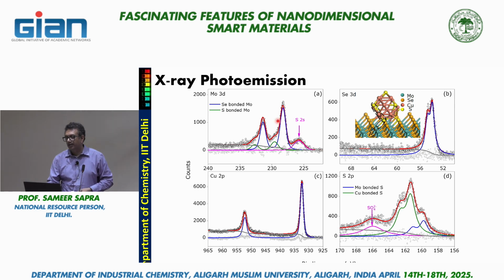and molybdenum is mostly bonded to selenium, so naturally I'd say fine, this large peak should be the one that is bonded to selenium. The small peak should be the one that is, I've also added the dodecanethiol and now it's formed cuprous sulfide, but that sulfur has bonded to molybdenum. And also, if I look at this, it's got a larger binding energy. Now sulfur being more electronegative, the molybdenum that is bonded to sulfur should have a larger binding energy.